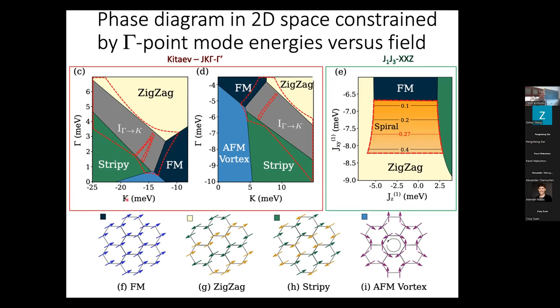What they find is that as you vary K and J, gamma, while keeping, by being able to describe the other data, then you're able to generate these different kinds of phases within the Kitaev model. However, within the Kitaev model, you can only generate an incommensurate state with a wave vector that goes between the gamma and the K point. You cannot have, constrained by the other information, an incommensurate state with a wave vector between the gamma and the M point.